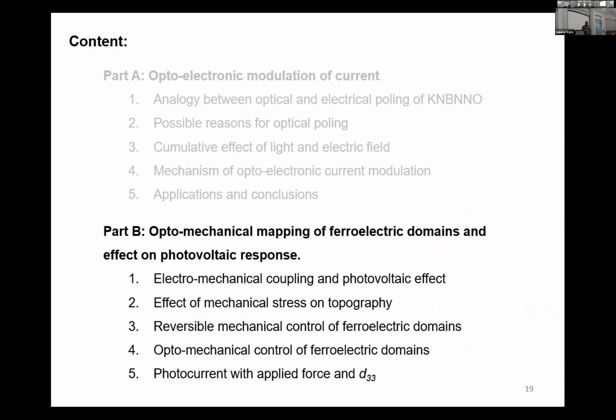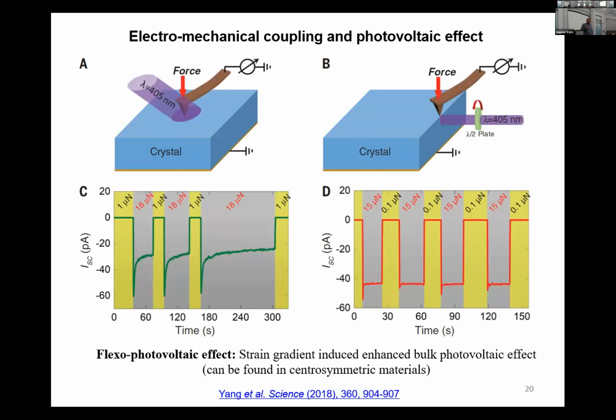Let me show you a few recent examples. So in this first example, there is electromechanical coupling with the photovoltaic effect. So what these guys did is they apply stress on a centrosymmetric crystal. It's not ferroelectric, it's not piezoelectric, but they apply the stress. They are shining light and they keep on changing the force. So you see with the force, the photocurrent is changing. There is a variation in the photocurrent when you increase the mechanical force. It's depending on the direction of light, where it is coming, and the polarization of the light. They termed it as a flexo-photovoltaic effect.